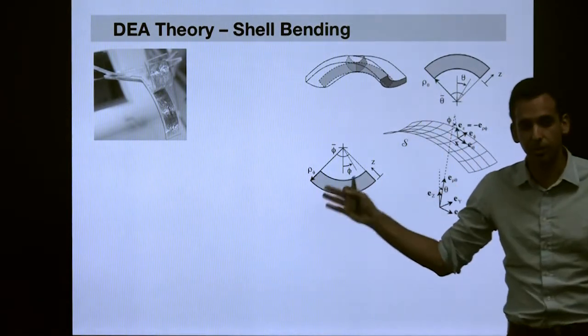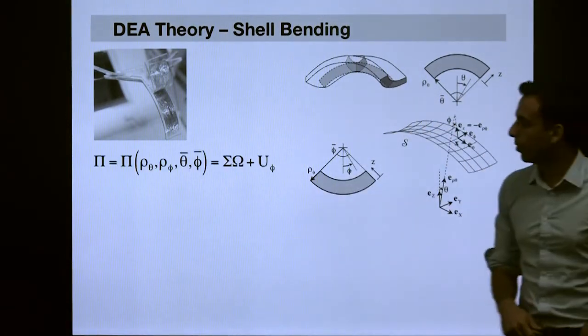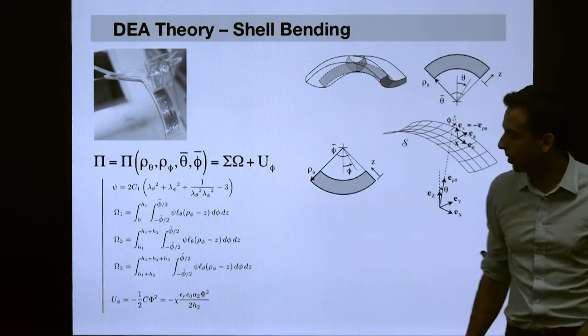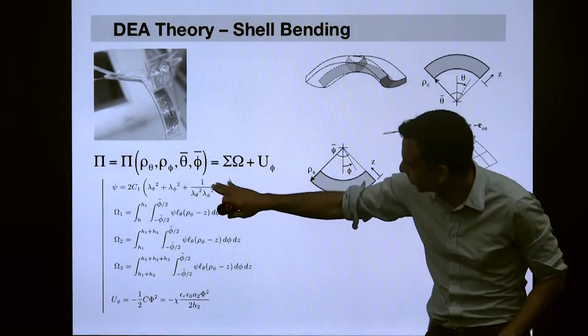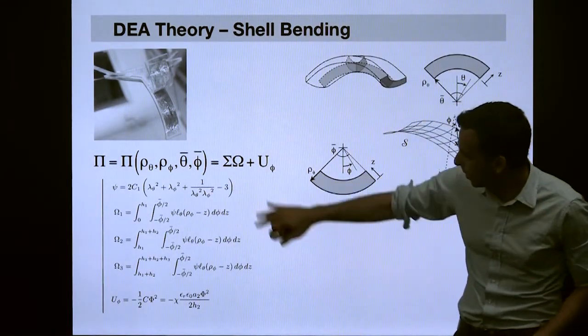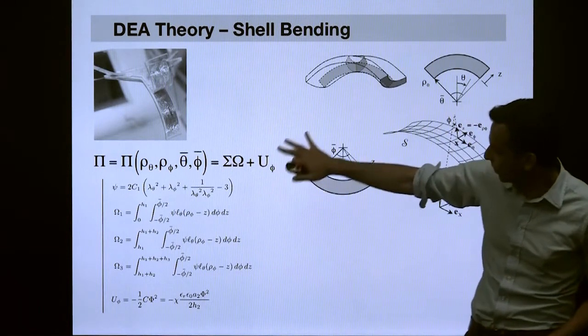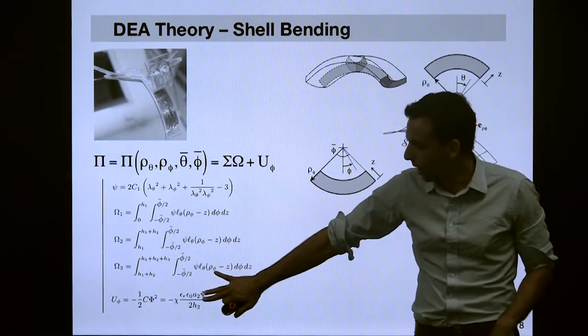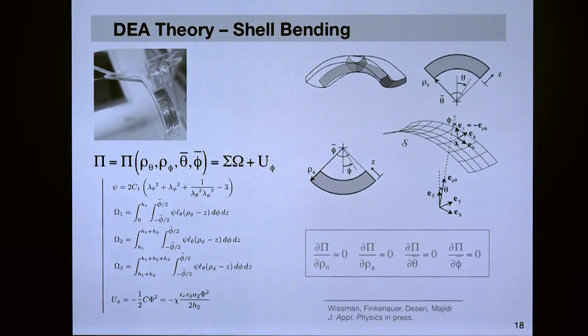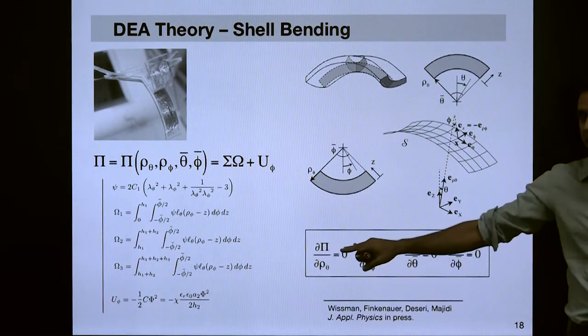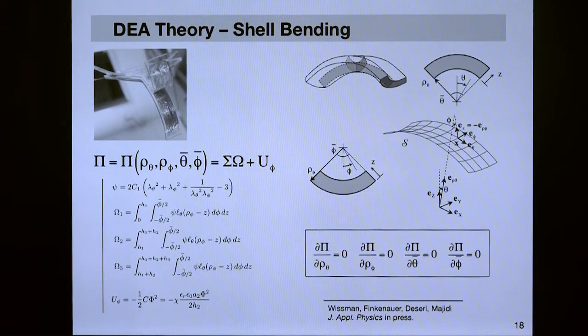We take the principal stretches and plug them into our constitutive model for an Ogden solid. Actually, in this case, I used a Hookean solid. Then we take the volume integral of that. We now add the electrical enthalpy. We take that total potential energy and minimize it with respect to all our kinematic parameters, in this case the bending curvatures and the corresponding arc lengths.